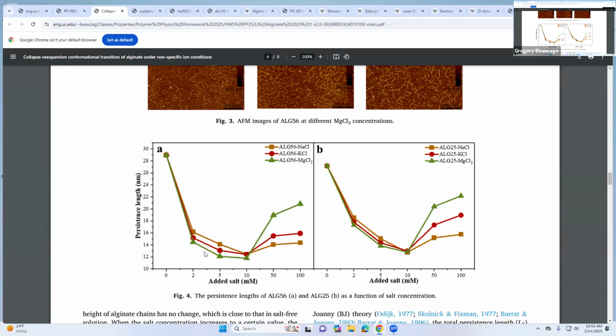That's just based on the Debye screening. So you add in the counterions, they screen out the charge. You add in enough counterions, the thing becomes as if it has no charge at all. The charged one is like a rod, it's fully extended. When you put in enough charges, it gets more worm-like, and then it becomes like a random walk. When the charge is washed out completely, if you keep adding charge, it still has some little bit of charge. Then you keep adding charge and this balloon effect comes on, where these big bulky cations stuck to it straighten it out.